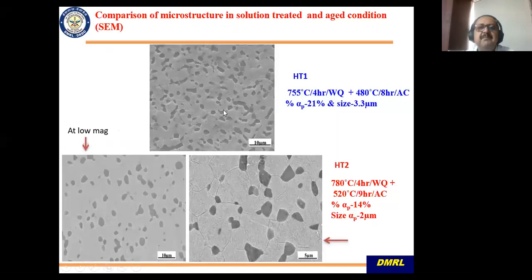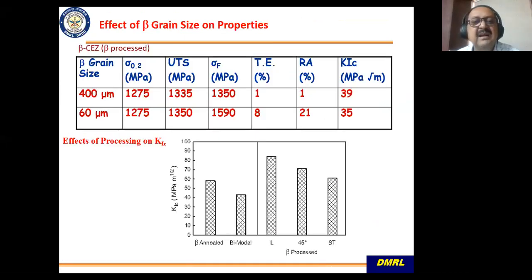This is the microstructure. So you have a beta grain here, which is pinned by primary alpha, and then inside these grains you have very fine precipitation of secondary alpha, and that gives strength. And this is the effect of grain size. Beta treated grain size plays a very big role in elongation. So reduction of the grain size does play a major role in increasing the ductility of titanium alloys.